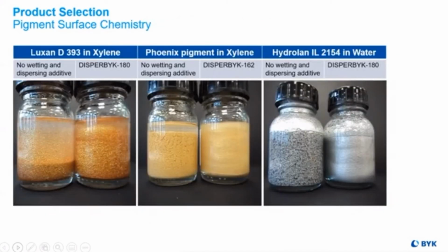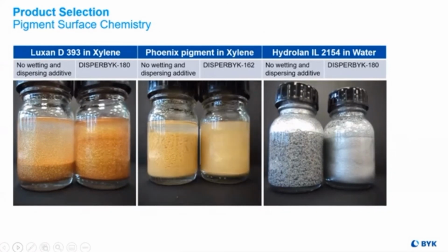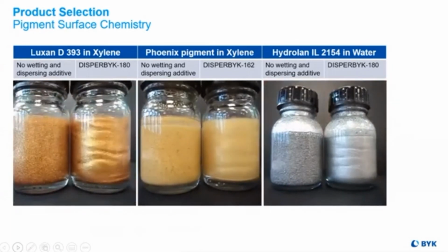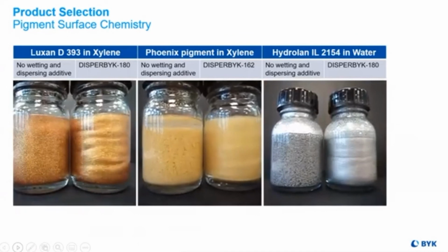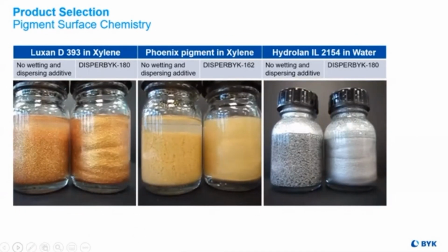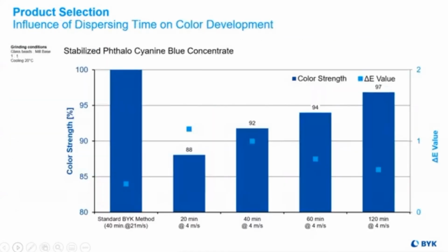Taking into consideration any treatments on the pigment surface, noting that those pigments that tout easy to disperse may still benefit from using proper wetting and dispersing additives. Along with ladder studies, grinding time evaluations may prove that the right additive can not only decrease grinding process time, but also can have a very positive effect on delta E values.